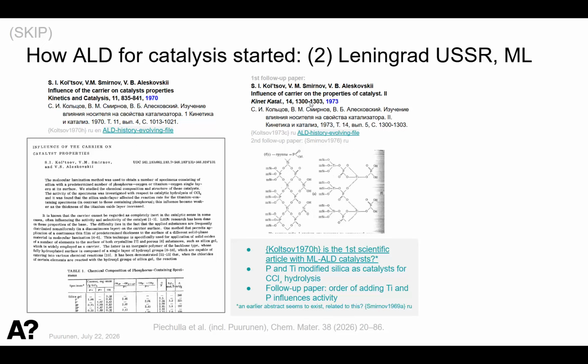So here is information copied from there, and this is from the translation into English of the paper that was originally published in 1970, first in Russian in Kinetics and Catalysis, Kinetika i Kataliz. And it was about the influence of the carrier on catalyst properties, and the scientists in Leningrad were adding phosphorus and titanium, modifying silica with those, and doing carbon tetrachloride hydrolysis. And then there's a follow-up paper a few years later where they were changing the order of this ALD modification of silica and found that that affects the catalytic activity. And these are real scientific articles.